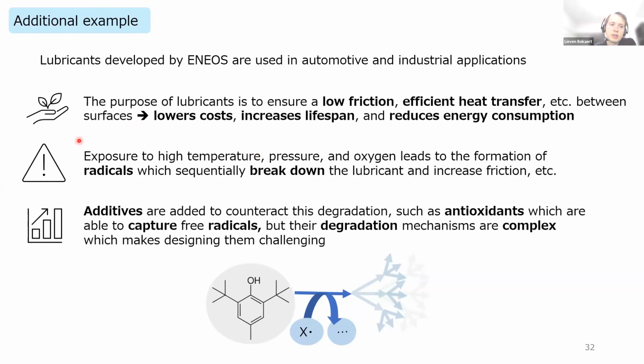Now, as you can expect, when you have different materials rubbing very quickly over each other, and also exposure to high temperatures, pressure and oxygen, this can lead to reactive species being formed. And one of those species are radicals, so single electron containing molecules. And these sequentially break down the lubricant and increase friction and other negative influences, which of course is very detrimental to the performance. And that's why we add additives to counteract this degradation.